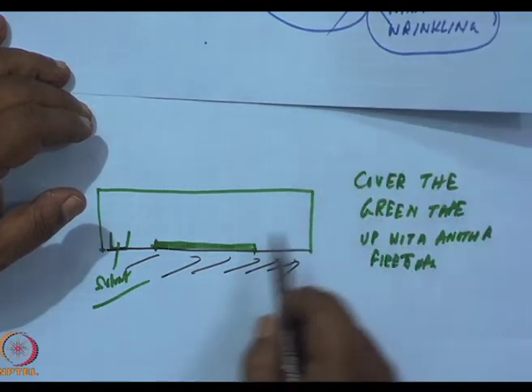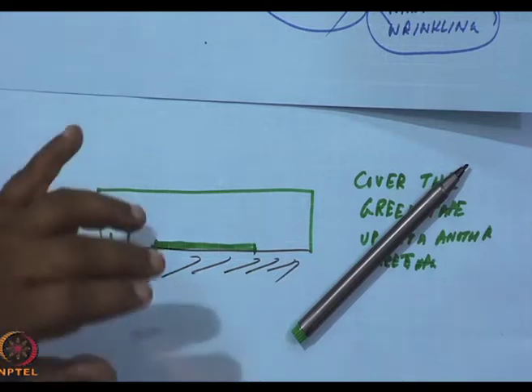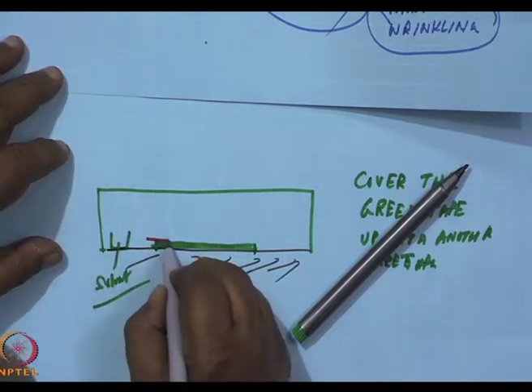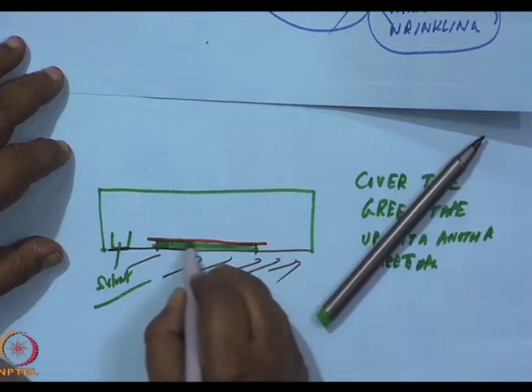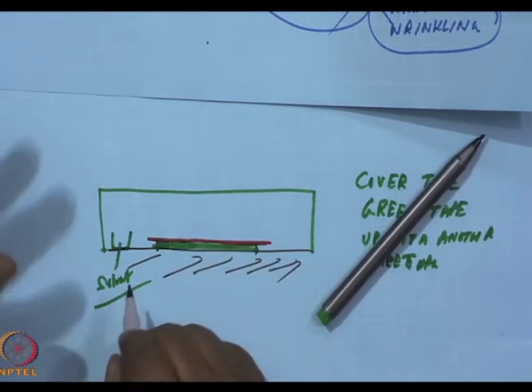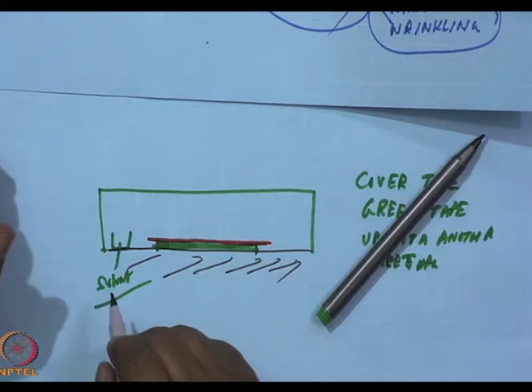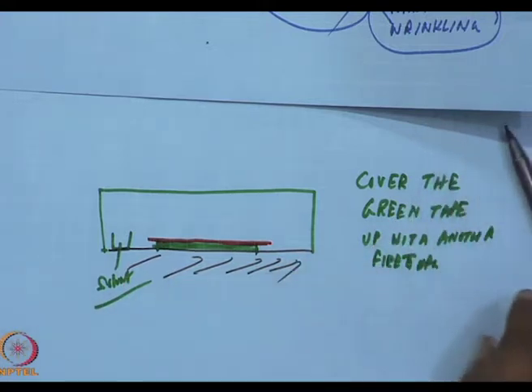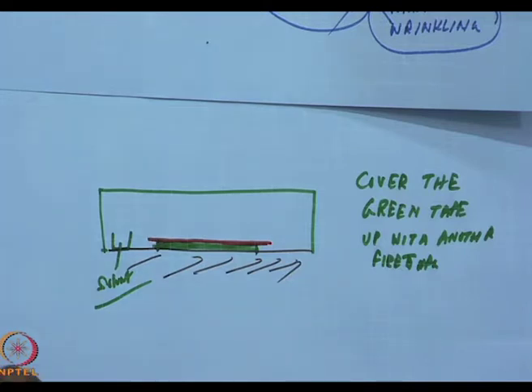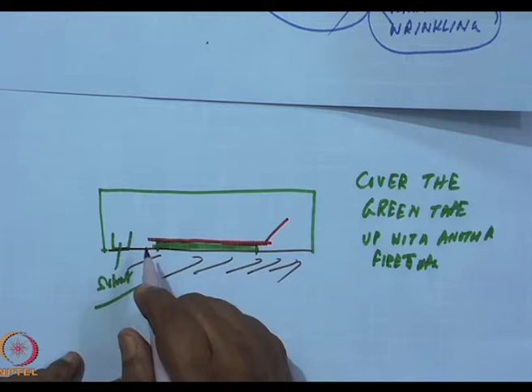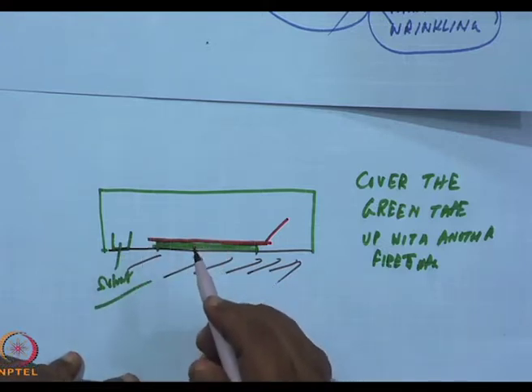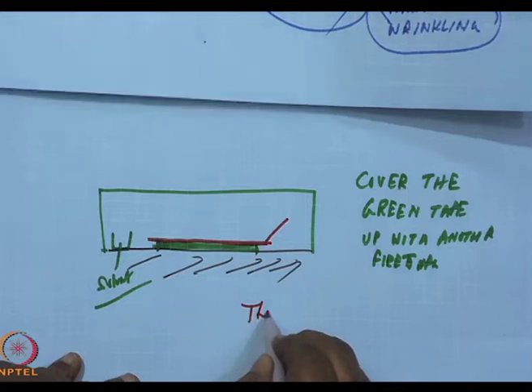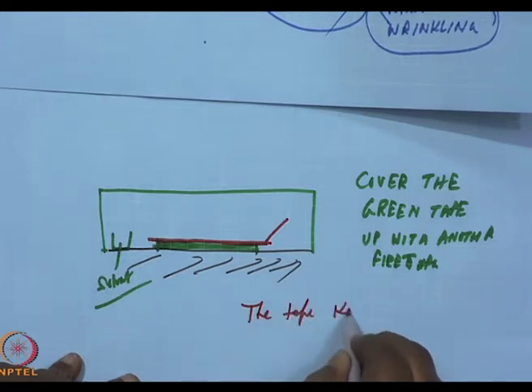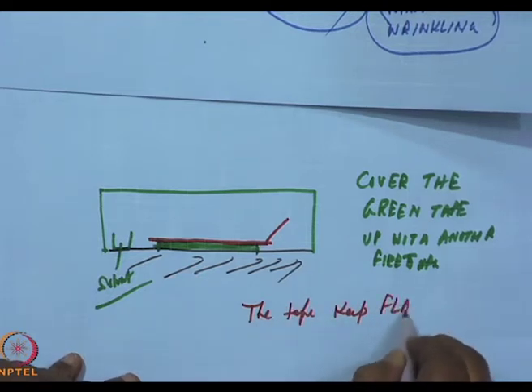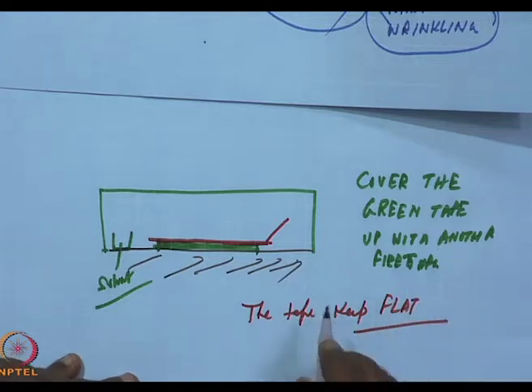The whole idea is, if I have a fired dense similar tape on top after casting, what would happen? The pressure of this material would help the tape keep flat and not wrinkle.